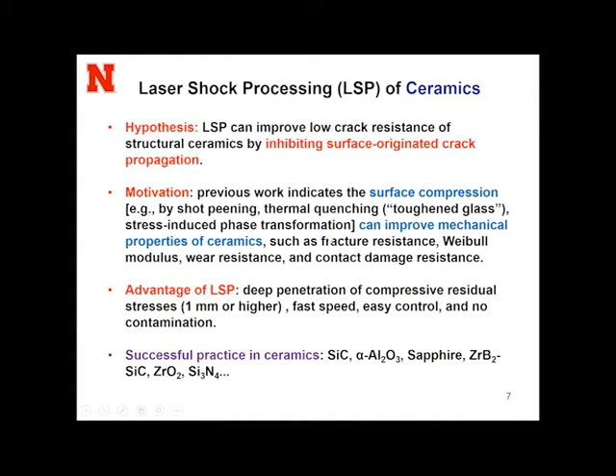But compared to those previous works, the reason we use LaserShock peening is the advantage of generating a much deeper compressive residual stress, which can be 1 millimeter or higher. And by using the laser to control the system, we have higher speed, easy control, and no contamination. So far, we have found several ceramic systems that are successful for LaserShock peening, including alpha alumina, silicon carbide, silicon nitride, and zirconia.